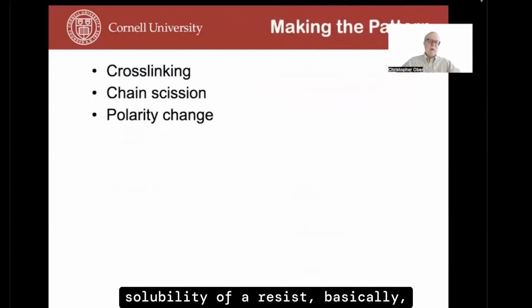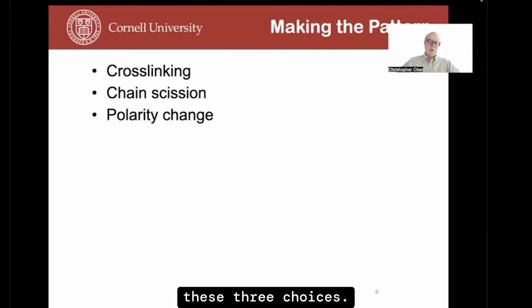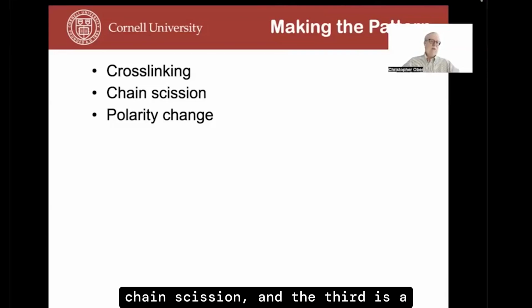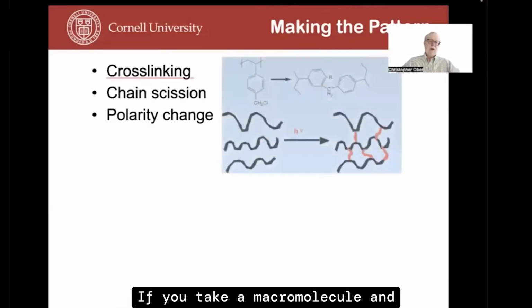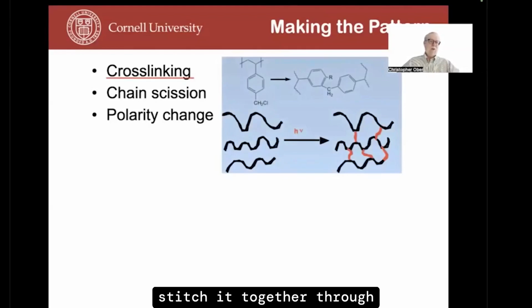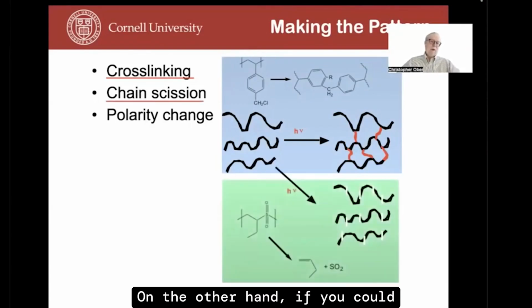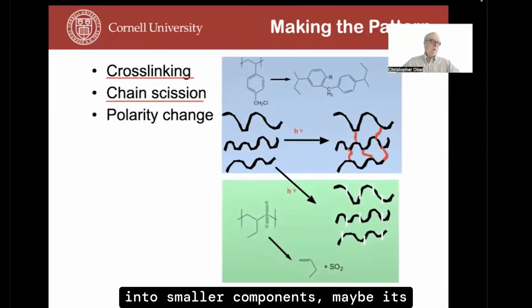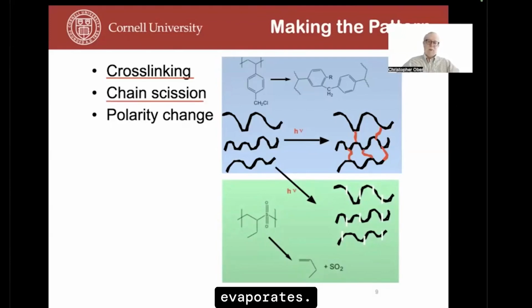So if we want to change the solubility of a resist, basically, and this is even true of today's inorganic systems used in extreme ultraviolet lithography, you basically have three choices. One is cross-linking, the next one is chain scission, and the third is a polarity change. Now, typically a resist is a polymer, so a high molecular weight macromolecule. If you take a macromolecule and stitch it together through cross-linking into a network, the solubility is reduced. A big molecule is less soluble than a smaller molecule. And so this is a method for producing a negative tone image. On the other hand, if you could take a polymer chain and break it into smaller components, maybe its original building blocks, that improves the solubility, or in some cases makes it so volatile that it evaporates. And that's a method for making a positive tone resist.